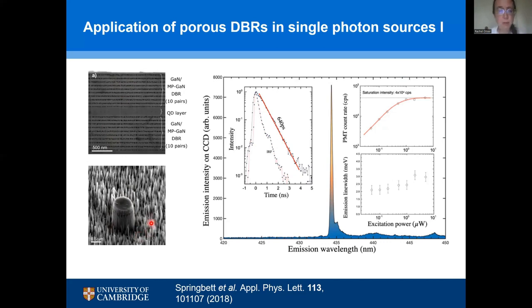So they're somewhat surrounded by what you might call like grass of gallium nitride, because the etching process to make the pillar has been disturbed by the porosity. And we've done some optimization to reduce that effect since. But this is the device we actually did quite a lot of the optical work on. So these are now data taken at low temperatures, and we're looking at single quantum dot emission from these devices. And we can get very, very high numbers of counts per second out of a quantum dot because of the extraction efficiency we're achieving using these distributed Bragg reflectors.